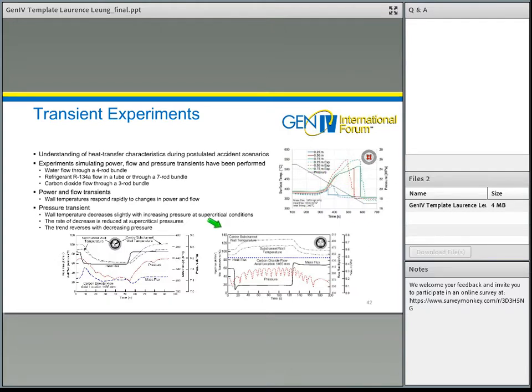And we also look at the three-rod bundle. This is the power transient simulation. It's basically you drop the power by 15% for some time, and then increase it back to the normal condition. You can see that once you drop the power, the system parameters also vary with the changes. And then it takes some time for the flow, for example, to stabilize. And the wall temperature actually follows quite closely with the changes.